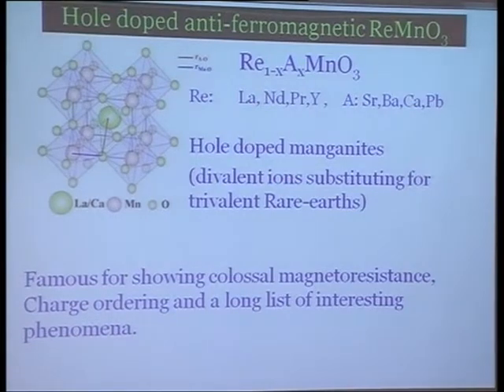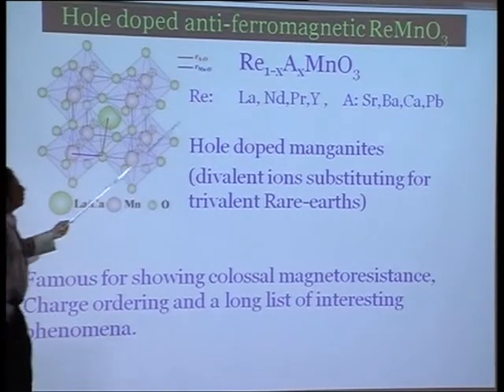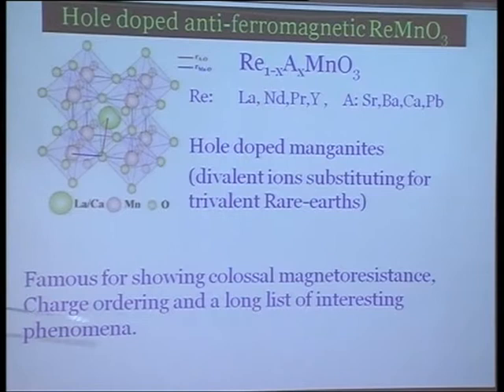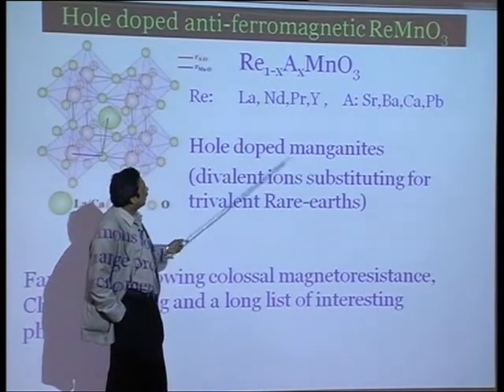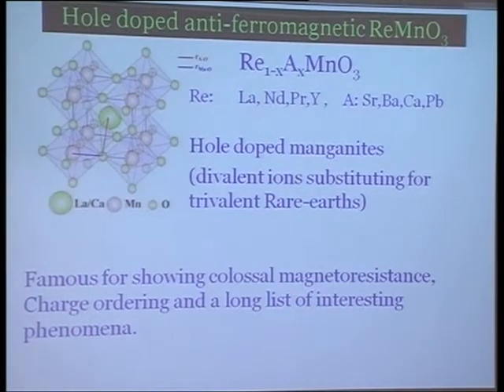Anytime. Okay. Now if you have an antiferromagnetic manganite and you hole dope it, this whole field of colossal magnetoresistance comes from that. This is just for my younger friends who may not be into this kind of field: this is the type of complex material one is talking about, and it is this particular bivalent substitution that you do and you create hole doping. So it is essentially a hole doped antiferromagnet that one is talking about over here.